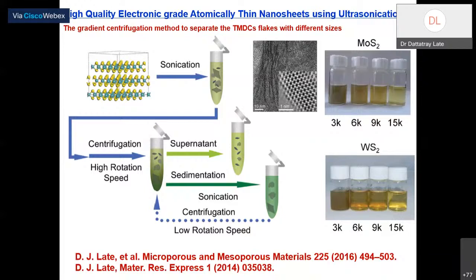Anywhere, even in a very simple college where I don't have any facilities. So I take this particular MoS2 powder or WS2 powder, any powder. I just need a very simple ultrasonication. I put the material in an ultrasonicator, for example, in some cuvette, with some solvent, maybe KOH, NaOH, or acetone, or NMP. NMP is best because that gives you a very good result.